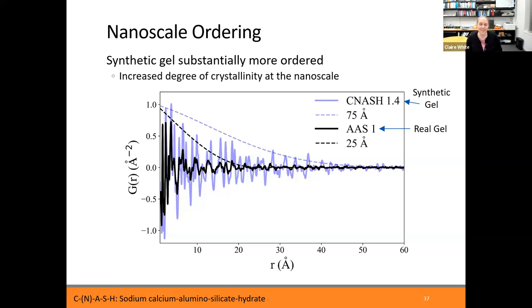That's great. So the nanoscale ordering is different between the synthetic and real gels, which means that we want to be careful with the results that we get on these synthetic gels to calculate things such as the solubility product of the gel that then gets used in thermodynamic modeling. Because the more crystalline a phase is, typically that means it's more thermodynamically stable, which means that its solubility product is going to be different.